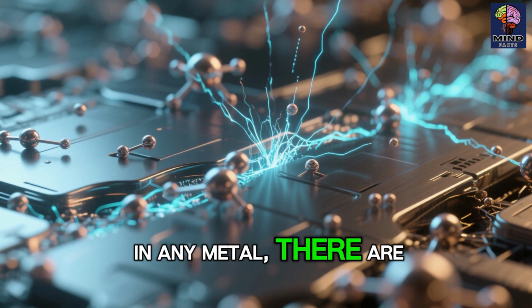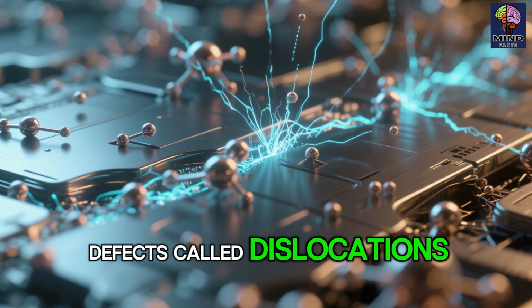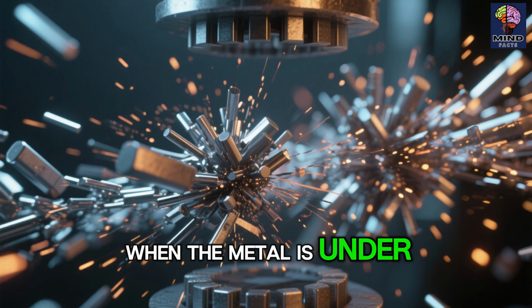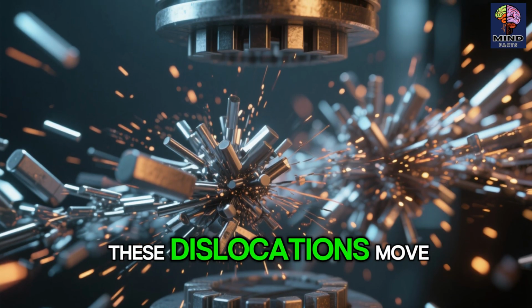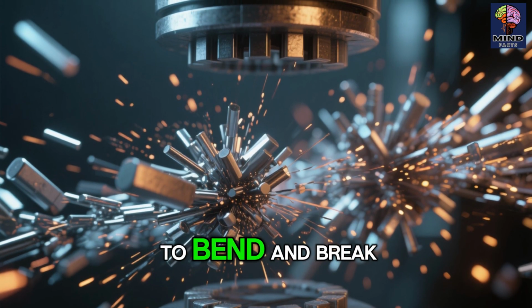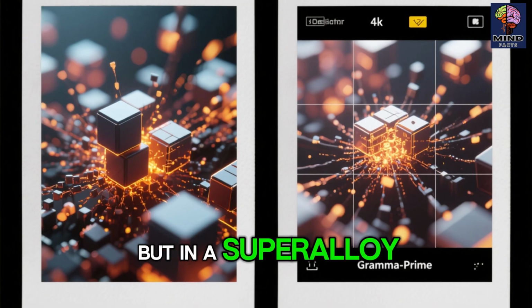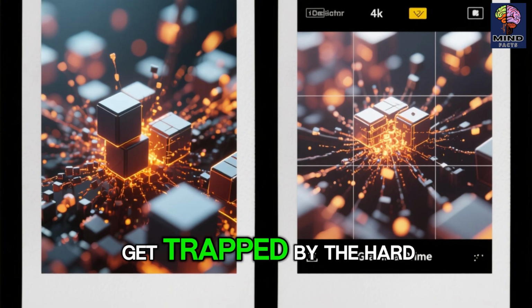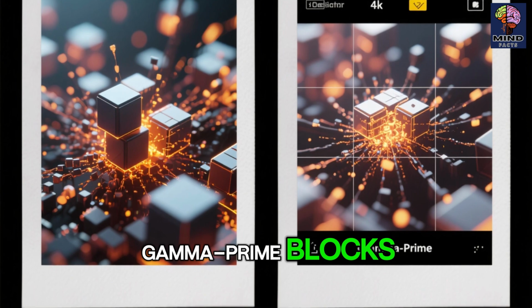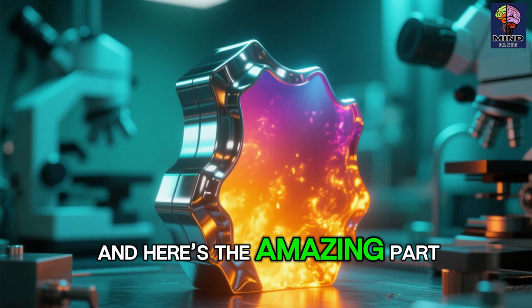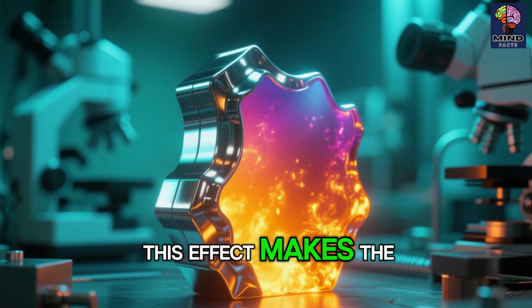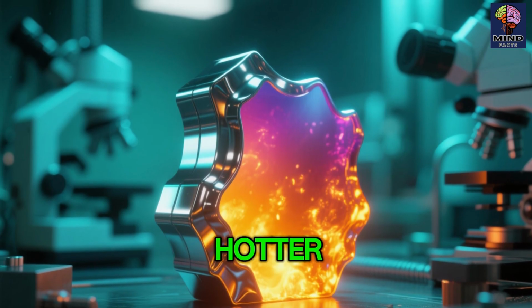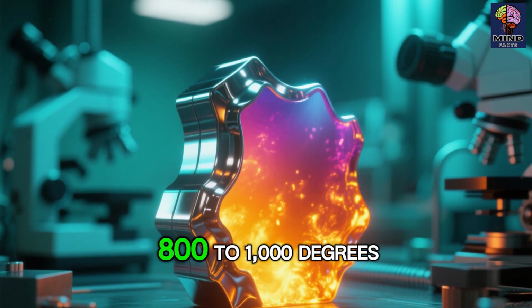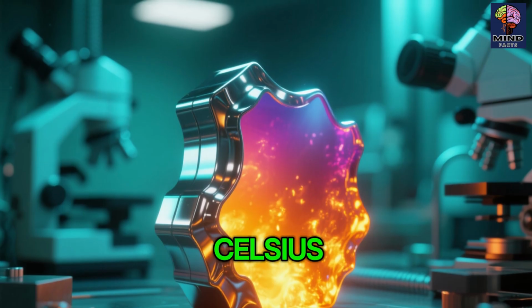In any metal, there are tiny atomic defects called dislocations. When the metal is under stress, these dislocations move, which is what causes it to bend and break. But in a superalloy, these dislocations get trapped by the hard gamma prime blocks. They can't move. And here's the amazing part. This effect makes the alloy stronger as it gets hotter, reaching its peak strength around 800 to 1000 degrees Celsius.